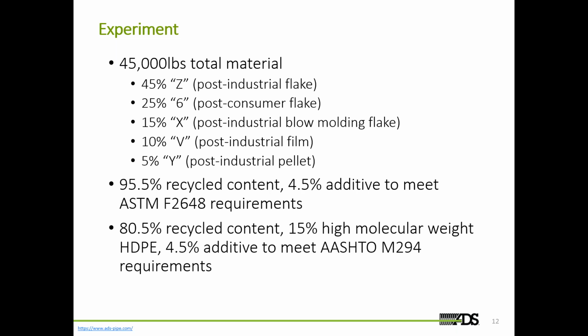It kind of broke down this way, where we looked at 45% of this total 45,000 pounds was post-industrial flake, 25% was post-consumer flake, 15% was post-industrial blow molding flake, 10% post-industrial film, and 5% post-industrial pellet. We actually made 2 separate pipe types out of this.